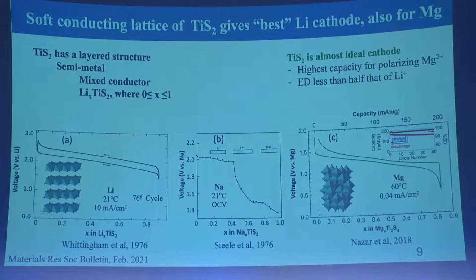I show you a plot here on the left-hand side. This is a lithium TiS2 cell from way back when, running at 10 milliamps a square centimeter. Extremely thick electrodes, far thicker than would ever dare use today. And the charge and discharge plots are separated just by the resistance of the electrolyte there. And it's a nice smooth curve, which means it's like a gas gauge in your car. So by measuring the voltage, you know exactly how much energy you've still got left there.